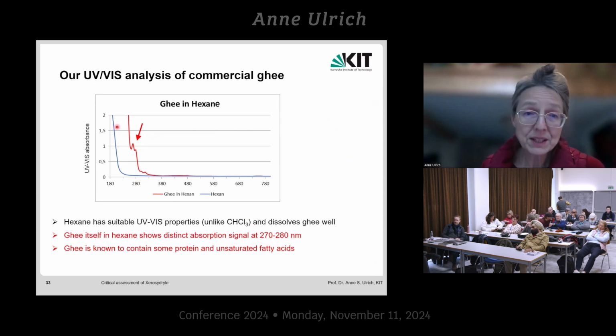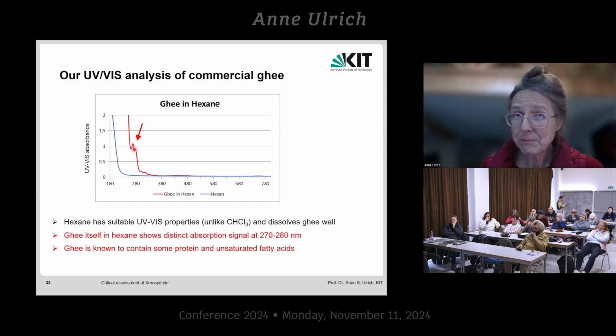So the first thing we did was to buy some ghee and dissolve it in a solvent that has a suitable UV-vis range to allow us to detect this component. And indeed, in ghee, there is a strong component at 270, 280 nanometers. This could be due to protein, but there is known to be just a very small amount of protein left in ghee because it's clarified butter without the protein.